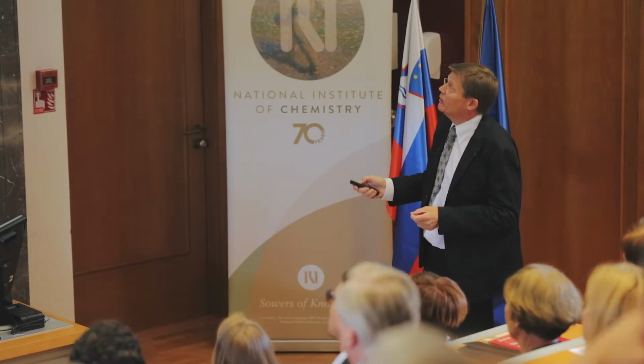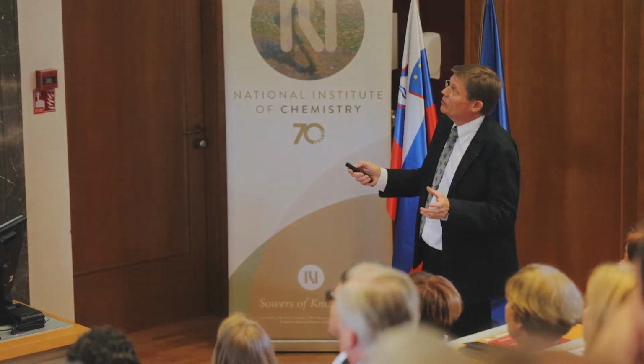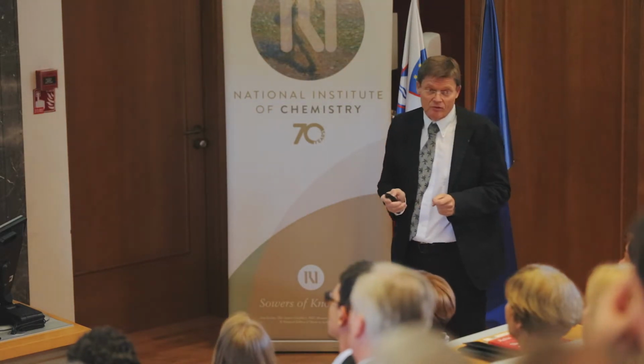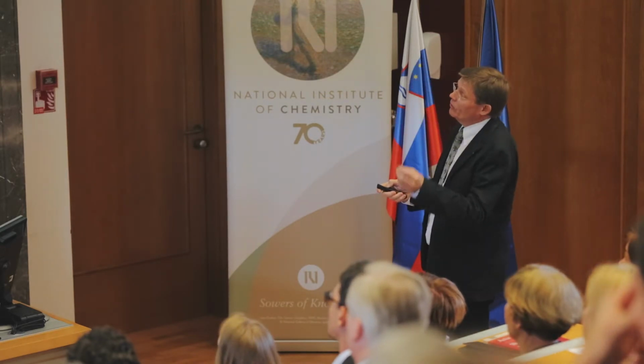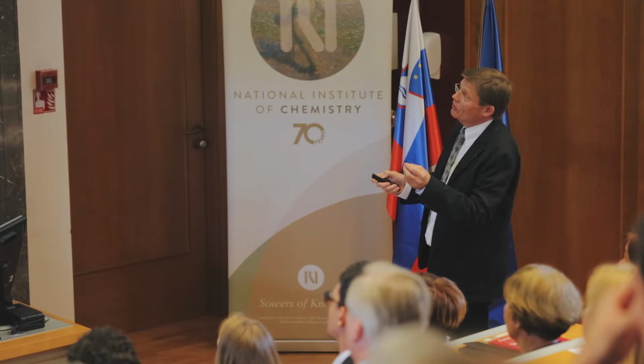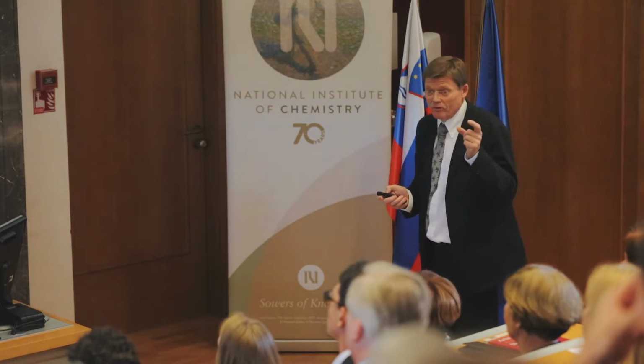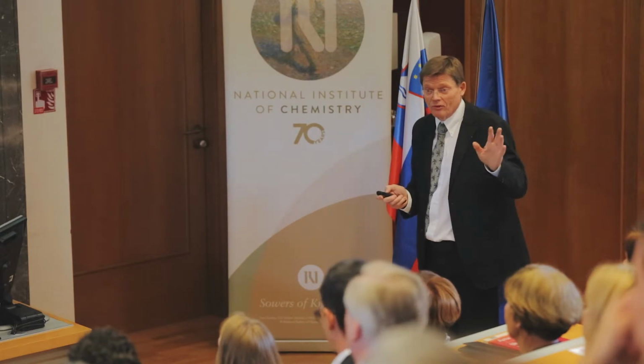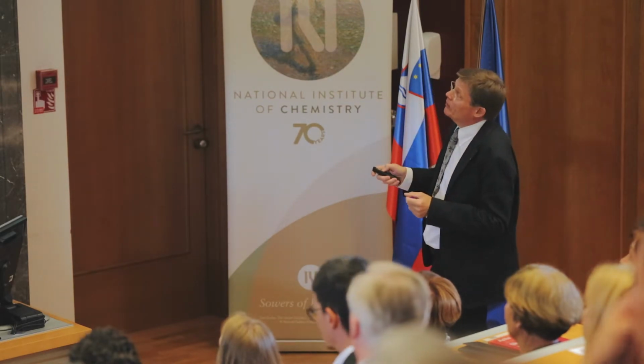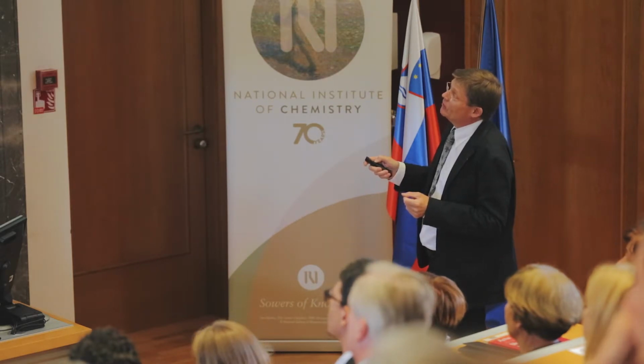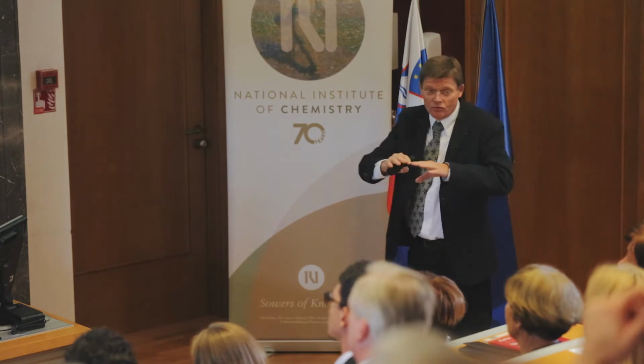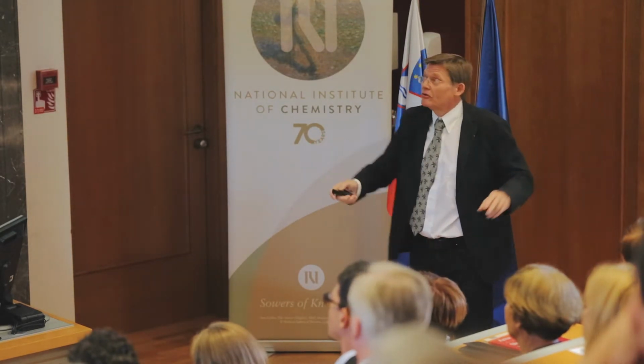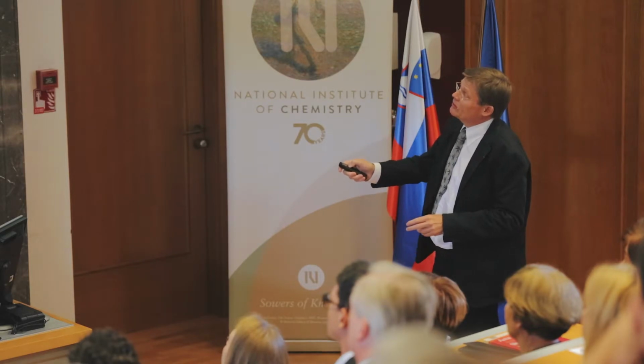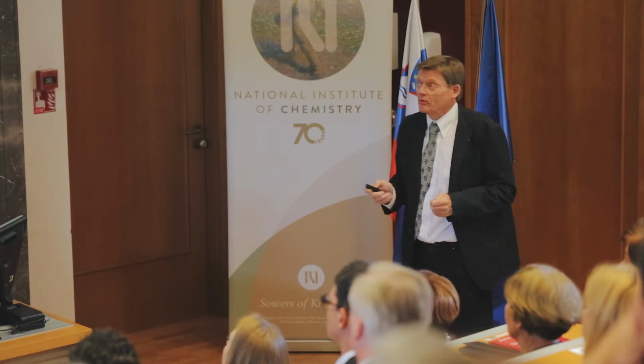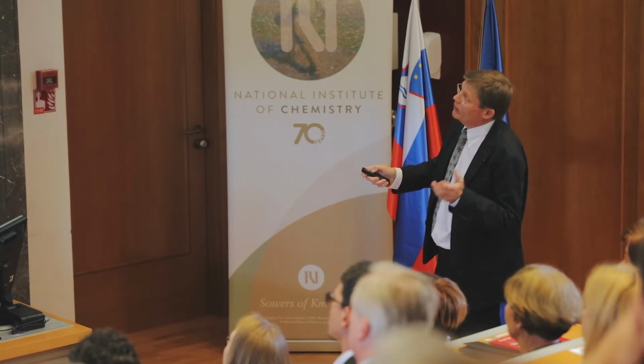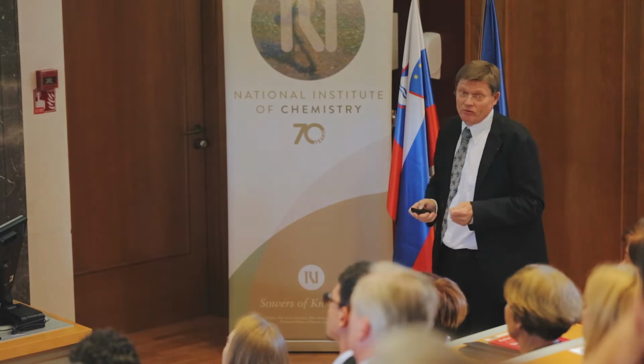It is shown a very old example, silver telluride, where you have pretty high silver ion conductivity and also some electronic. Now when you switch on your current, your voltage jumps to this voltage. This voltage is given by the total resistance, ions and electrons; initially, both contribute. But then in the course of time, the ions are blocked. And in the steady state, you have only the electrons going through that system. So this distance and that distance tell you how much electrons and ions you have in the system. So here you have probably 80% ionic conductivity and maybe 20% electronic.